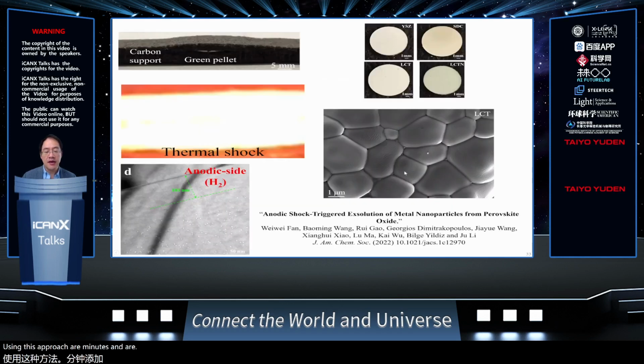And indeed, you can even sinter the powders to pretty high density. And by using this kind of voltage pulse, you can also induce exsolution of metallic nanoparticles embedded in these ceramic electrodes. So by using such extreme processing, with very short duration, milliseconds, and sometimes even down to 10 nanoseconds, but pretty extreme conditions, you can achieve extraordinary microstructures in systems.